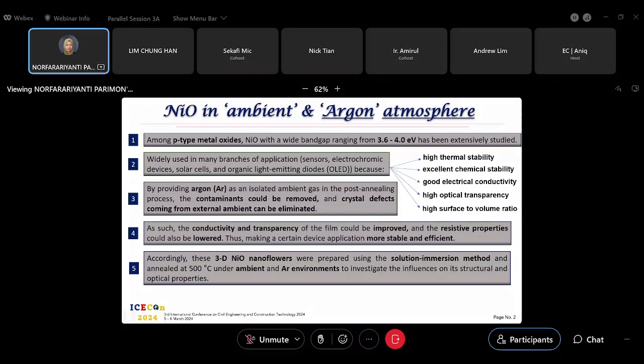So by providing argon as an isolated ambient gas in this post-annealing process, the hypothesis is that the contaminants could be removed, and the crystal defects coming from the external ambient can be eliminated. As such, the conductivity and the transparency of the film could be improved, and the resistive properties could also be lowered. And then it makes certain device applications more stable and efficient.